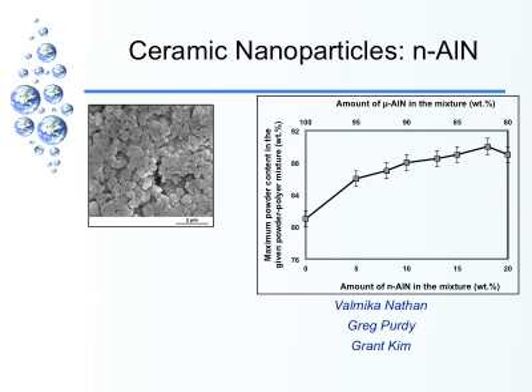And what he found out was, this is in weight percent, what is the maximum content of the powder in the polymer. Okay. What is plotted here is the ratio of micro to nanoscale particles. Okay. So two things you can observe. If you change the ratio of micro to nano, the maximum packing density changes, and it goes to close to 91 weight percent, which turns out to be close to 72 volume percent, right? So you had one powder that had a maximum packing density of about 54 volume percent. You filled it with another powder that had a maximum packing density of about 40 volume percent, but the combined mixture in some ratios allowed you to get close to 72 volume percent, which is really high for ceramics used for injection molding.